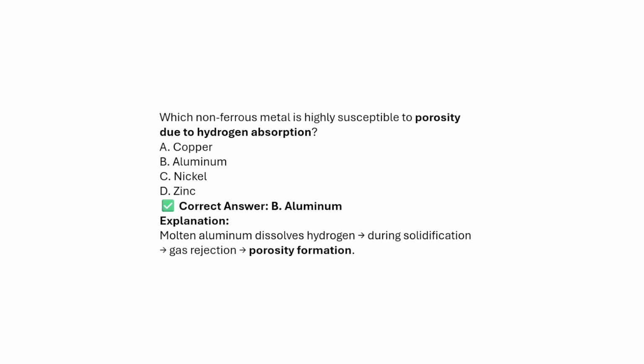Which non-ferrous metal has the highest susceptibility to porosity due to hydrogen absorption? The options are copper, aluminum, nickel, zinc. Which one? It is aluminum. So molten aluminum dissolves hydrogen, which during solidification is rejected as gas, causing porosity formation.